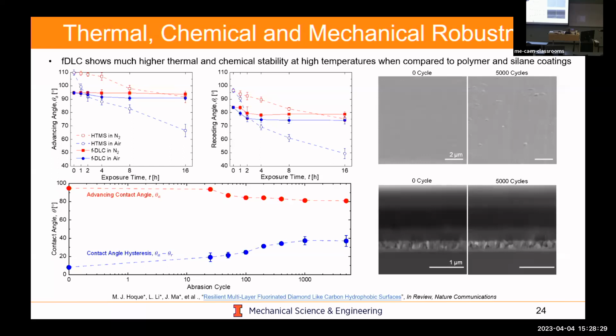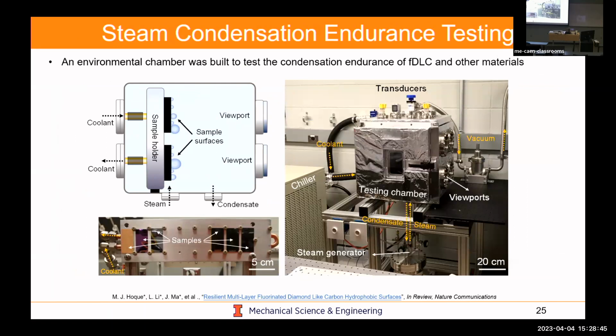So this is a SEM image, a FIB image, focused ion beam cross section at 0 cycles and 5,000 cycles, and these are multiple different layers. You can't really differentiate between the two after 5,000 cycles. So good, everything makes sense. Now, how long will it last?